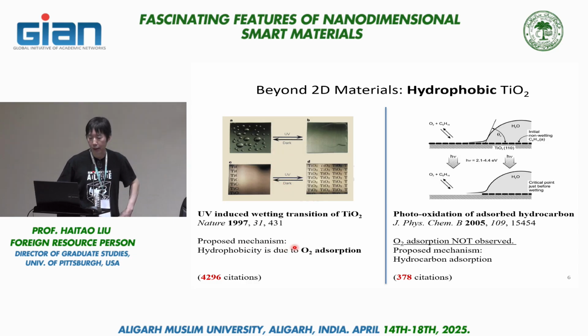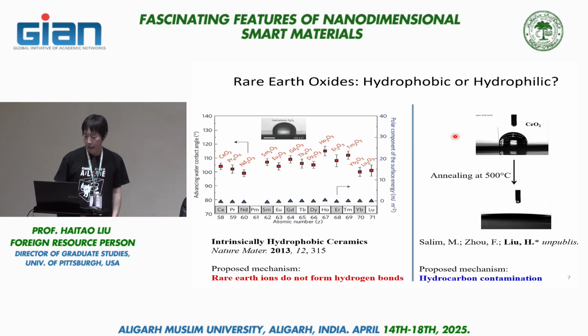The authors proposed that oxygen adsorption was the mechanism, and UV excitation kicks off surface-adsorbed oxygen. But later it was found that there's no oxygen adsorption on TiO2. What is happening is actually hydrocarbon adsorption, where UV oxidation on TiO2 oxidizes the hydrocarbon adsorbed on the surface, and that makes the surface hydrophilic. If you leave it in the dark, there will be natural adsorption of airborne hydrocarbon, which makes it hydrophobic. So it's the same kind of mechanism we observed in the 2D materials, but operating on the oxide surface. It's quite interesting that people have been making the same kind of, I don't want to say mistake, but falling into the same trap again and again.